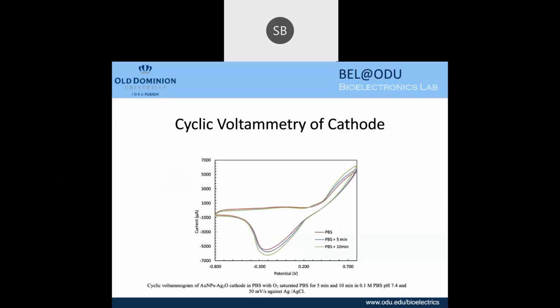This shows the cyclic voltammetry of the cathode, where it is apparent that the reduction current increases in the presence of oxygen, with an onset potential of 231 millivolts.